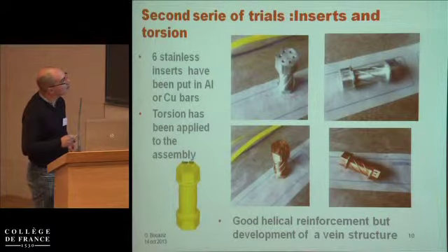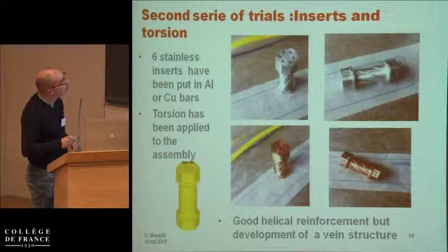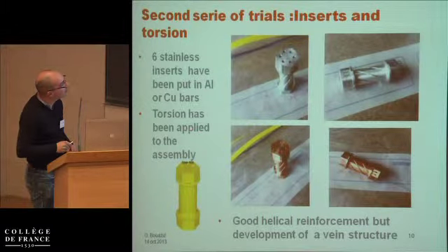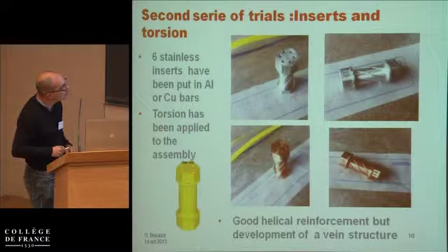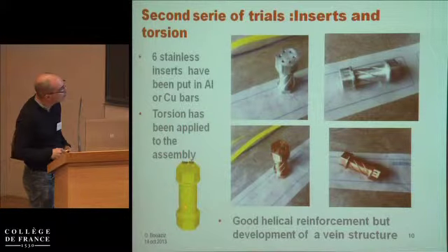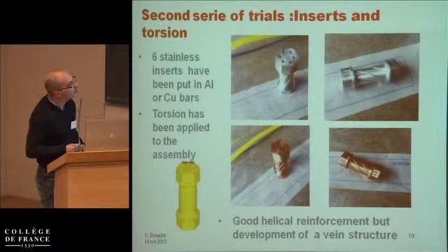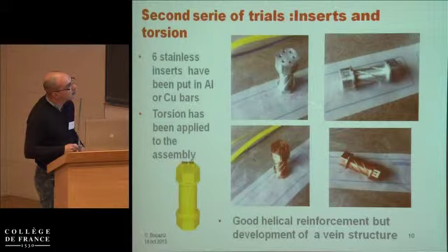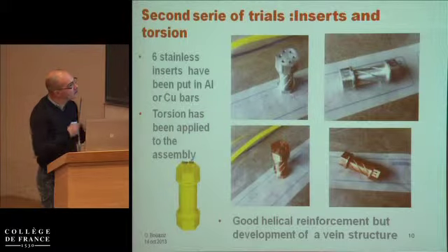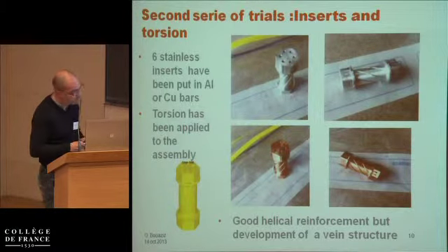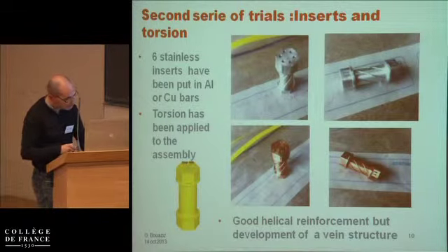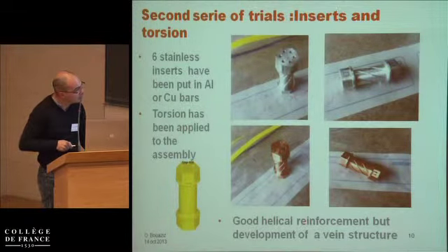A second series of trials has been done. We have put six stainless steel inserts in the aluminum or copper bars, and torsion has been applied to the assembly. You see here the six inserts along the sample, and after torsion, you see clearly that we have developed the internal helical reinforcement, but we have a vein structure. It means that the material of the insert has been pushed out during the experiment. We have a good helical reinforcement, but with development of a vein structure.